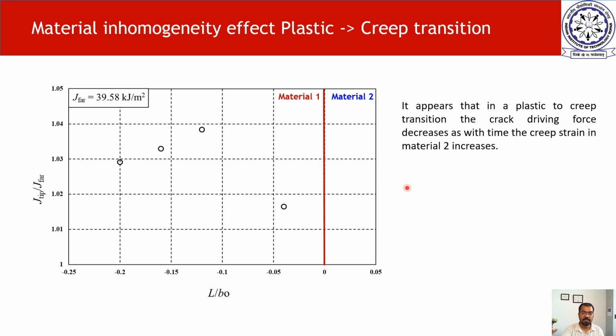And the effect of this shows that first the crack driving force increases, but it appears that even when the crack has not come very close to the interface, the behavior has reversed here. This is very different from what we found for elastic plastic case, but we have to confirm it more by taking more points at different crack tip locations closer to the interface.